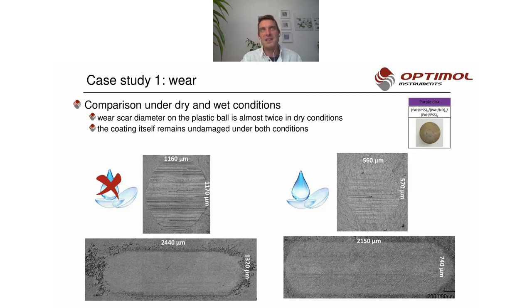The basic idea was you don't like to end up with some scratches on this coating or some chips coming out or something like this, and you would like to decrease your wear situation. You can see it already in these testing procedures, because those lines were more on the bottom. But you are able to have a very easy look on the scale here: less wear and a better friction situation. And then we tested all the other coating variants.